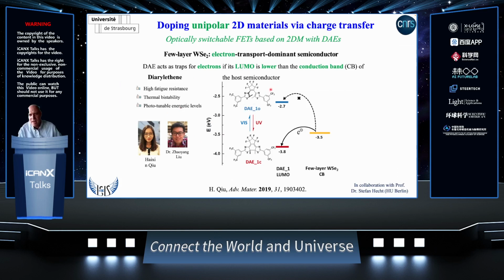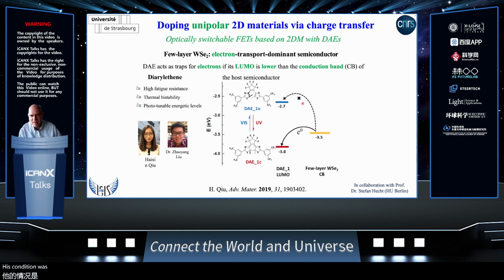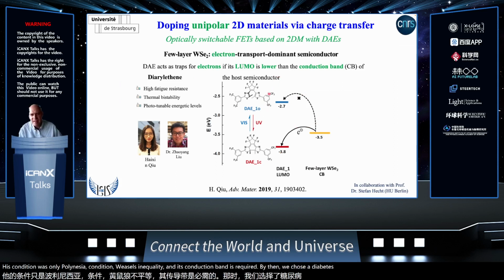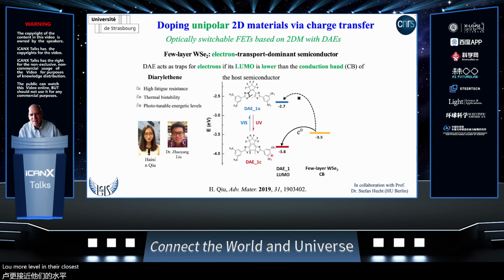We first of all focused on unipolar 2D materials, and we took tungsten diselenide that in this condition was unipolar, and this conduction band is -3.5. Then we chose a diarylethene such that its LUMO level in the closed state is inside the band gap of the tungsten diselenide, whereas when it is in the open state, it is out of the band gap.